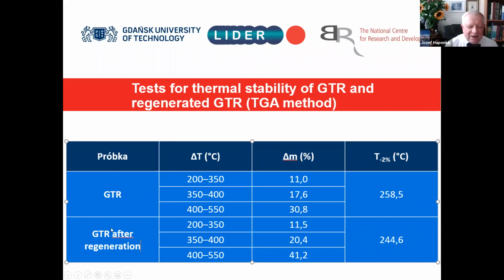Ground tire rubber GTR after regeneration have still the similar thermal stability. It means there are not too many low molecular weight products inside this reclaimed rubber, because the loss of mass between different temperatures is similar for untreated and treated samples.